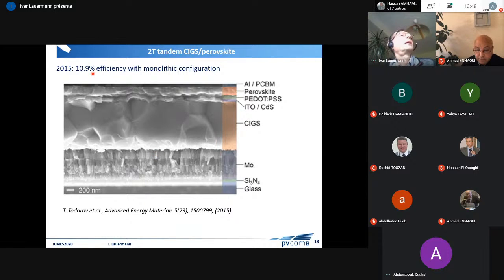The first cell in this scheme was shown in 2015 by Theodor Todorov. And here we have the CIGS bottom cell, the standard cell. Here we have a thin layer of conductive oxide and a hole conducting material. And only this thin layer is the perovskite top cell, and then aluminium PCBM, a top contact. And at that time, they had almost 11% efficiency.